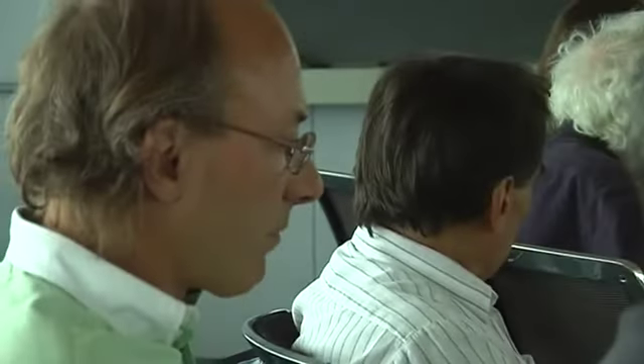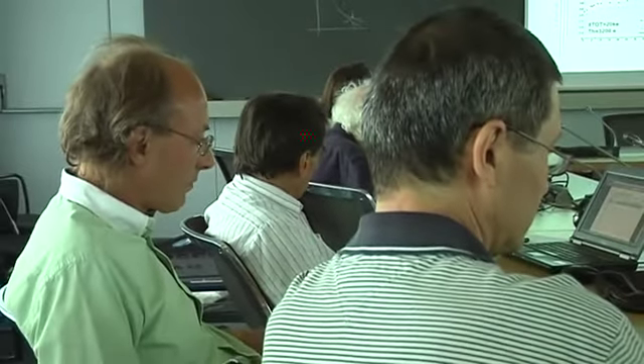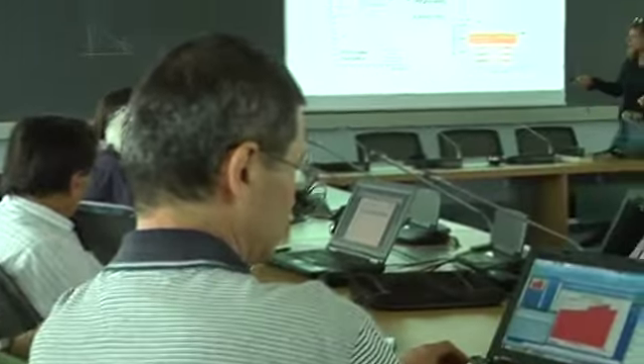Those measurements are showing TOT, with FEI4 devices versus bias voltage, and these are two devices, and you can see here that the most probable value again reaches a sort of plateau at just below 10 volts. So I think we are confirming this. This was taken with a tuning of a TOT per 20 kilo electrons, which is the same that we use in the test beam data, by the way, and a threshold of 3,200 electrons.